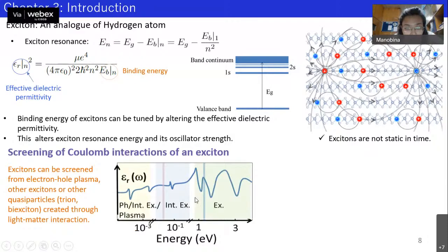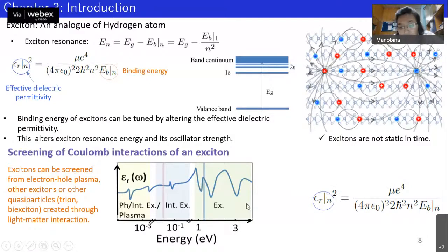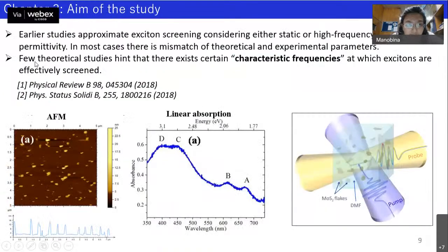So basically the dielectric function is a function of frequency. But if we see this equation, this is not a function of frequency, rather this is just a number. So now the question that we ask is, how is this frequency dependent quantity related with this constant number that dictates the excitonic binding energy. Now there are several studies, basically theoretical studies, that predict that there could be a characteristic frequency or a set of frequencies at which the excitons are effectively screened.